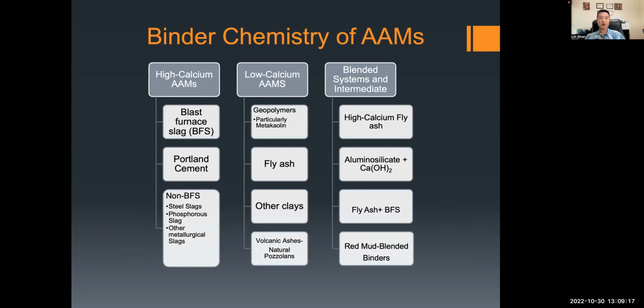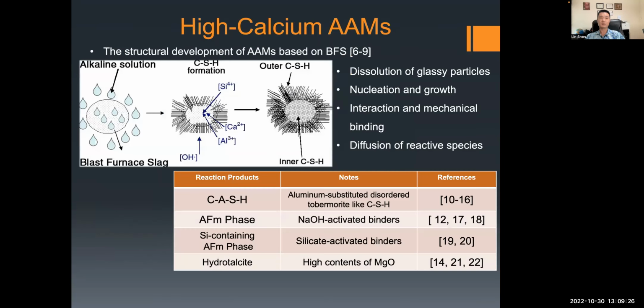And based on the chemistry of precursors, we have high calcium AAMs, low calcium AAMs, and blended systems. For high calcium AAMs, the reaction products include C-A-S-H, or aluminum substituted disordered tobermorite like C-S-H. We could have AFm, which is a classic phase in Portland cement, among other hydration products.